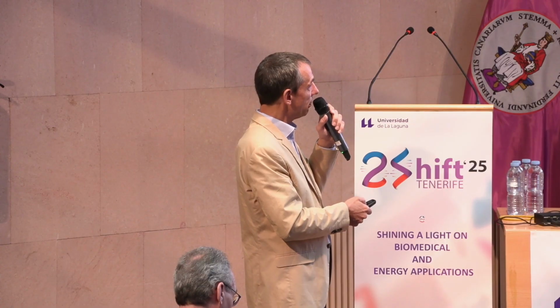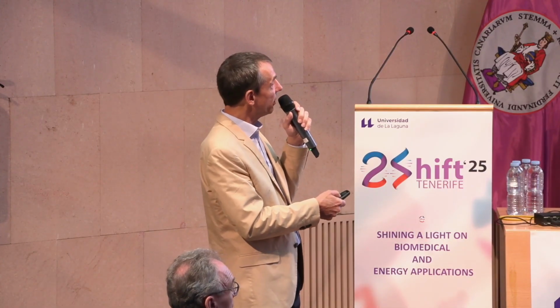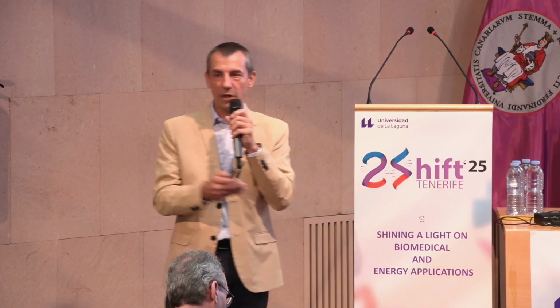And what about other molecular emitters? Well, now we have a quantum state lifetime which is 2 to 3 orders of magnitude longer than what you can have with other systems, single molecules, purely organic molecules, but also other complexes based on transition metal ions, for example chromium-4, which has also been investigated. So here we have a much, much longer quantum state lifetime. And this opens, of course, completely new possibilities for quantum communication and quantum processing. We can do optical spin addressing and so on. It's a very important feature if you want to use these systems for quantum applications.